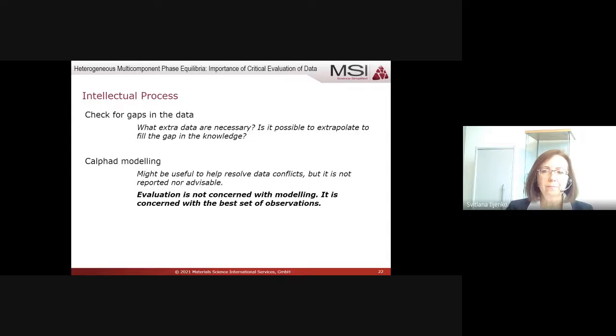So we check also for gaps in the data. Some publications, of course, report only a particular composition or temperature range. And it happens that in the literature we don't find data for particular regions in the phase diagram. Then our task is to check whether it's possible to extrapolate in order to fill the gap in the knowledge. At this point thermodynamic modeling is helpful, but not necessarily. It's also possible intellectually to give a suggestion on how to continue, whether it's possible to extrapolate in the unknown regions. And we try to be objective and not bring much speculation into this.